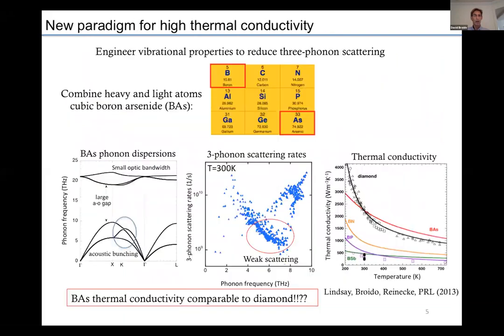But it turns out there's another way of achieving high thermal conductivity, and that involves engineering the vibrational properties of the material so as to reduce the 3 phonon scattering. And so this actually involves combining heavy and light atoms, so that goes against the conventional criteria. The best example of this paradigm for achieving high thermal conductivity that we found is cubic boron arsenide, which combines an arsenic atom with a boron atom, where arsenic is 7 times heavier than boron.